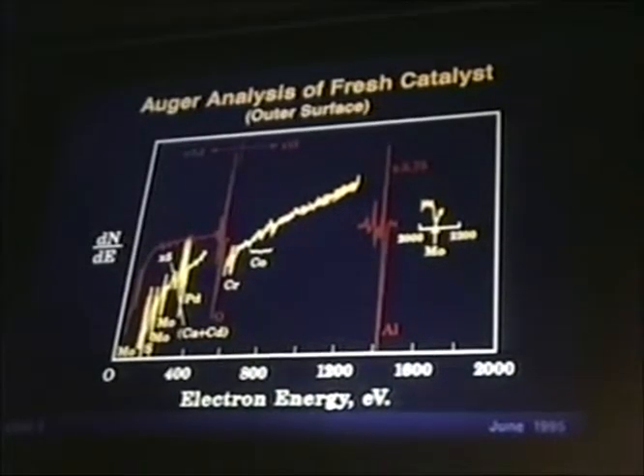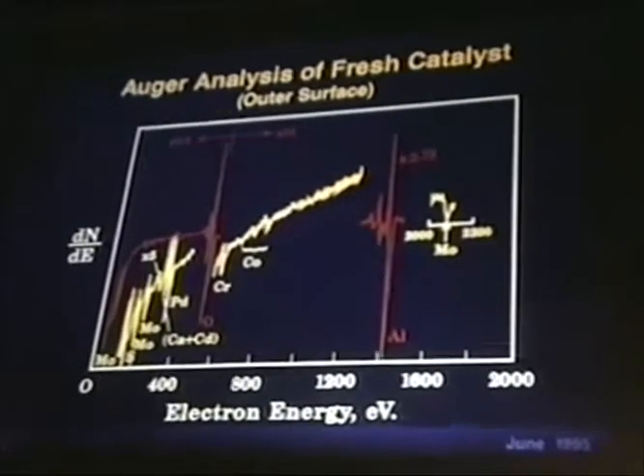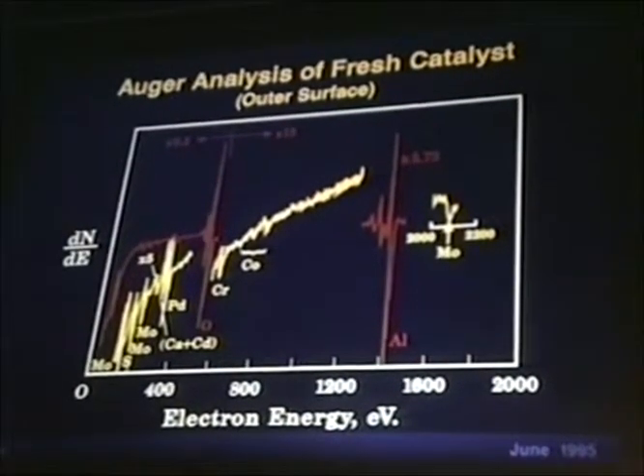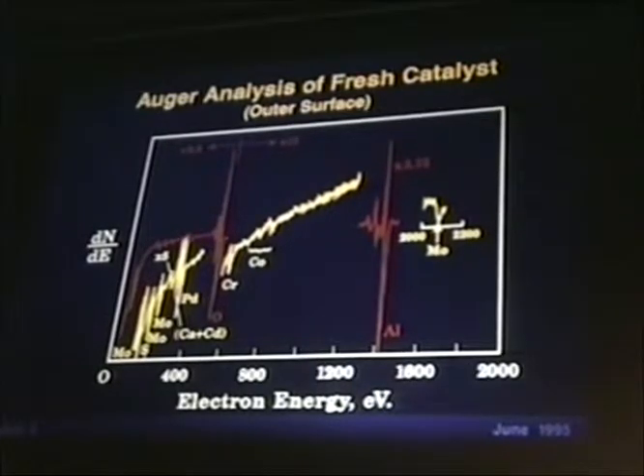Conventional analysis, including X-ray fluorescence, failed to show significant differences between fresh and spent catalysts. Bulk analysis showed only 0.16% iron, and that by itself is not necessarily a poison on a 200 square meter support. We found on opening up the reactor on the top that there were some rust particles, but on removing the rust particles, the catalyst still failed to rejuvenate.